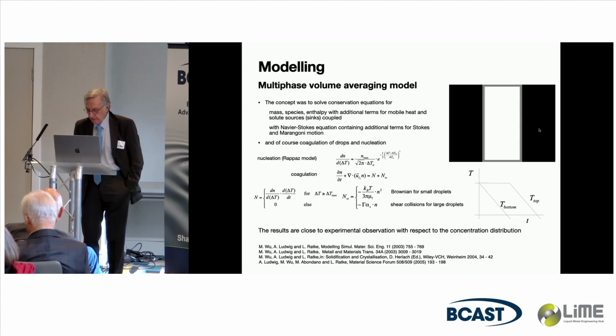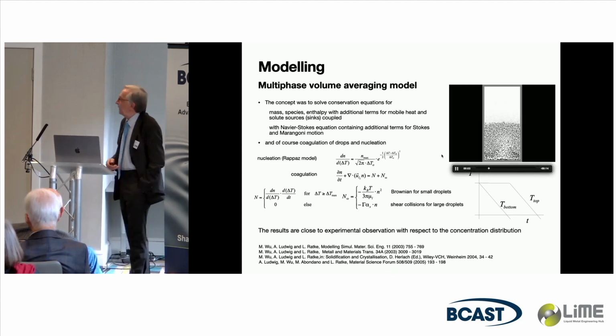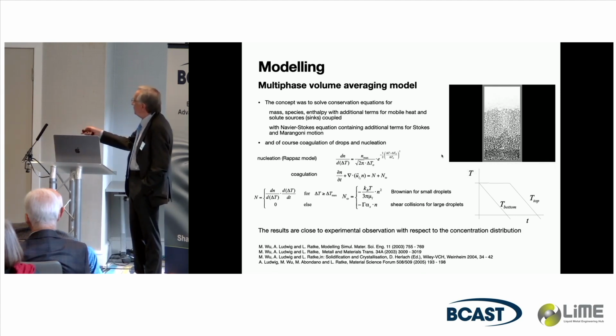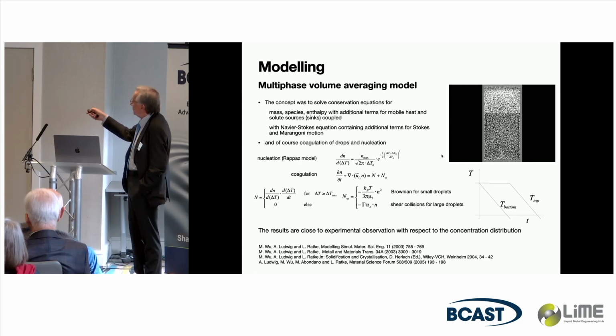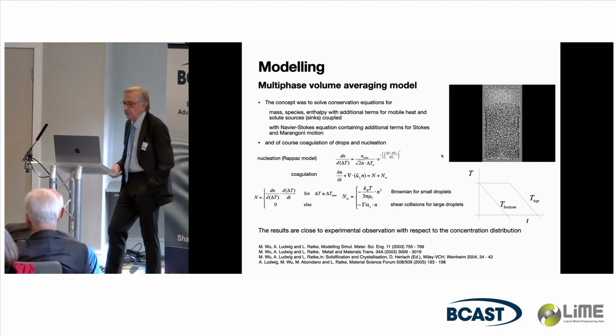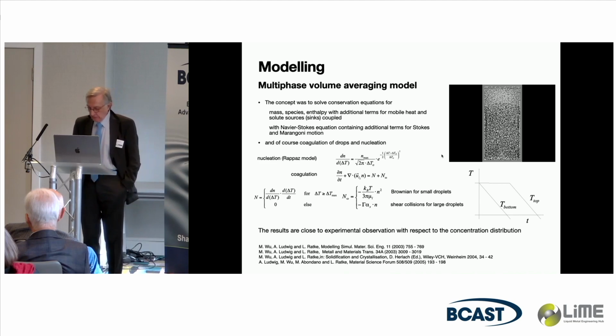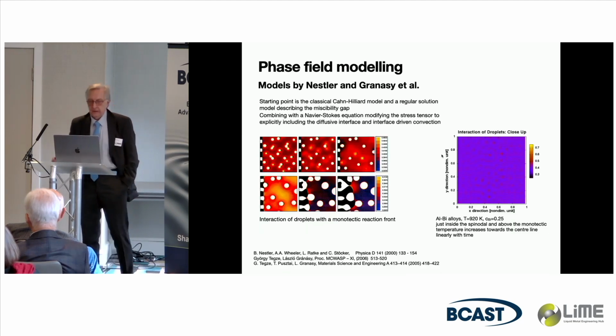And the fine thing is, I like this movie very much. You see cooling it from the bottom. Here is the cooling. You directly start with the cooling. You see that a lot of droplets appear. And since here the cooling also starts later at the top, this would be the final microstructure. And we could compare that with experiments. It generally is not that bad.